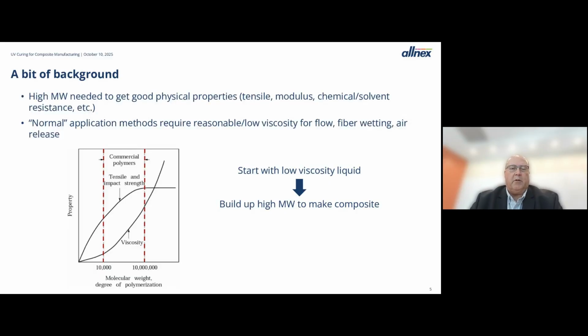So just a couple quick background slides. I'm sure that most people already know this, but just to get us rolling. In the world of polymers, in order to get good physical properties, good tensile properties, high modulus, chemical solvent resistance, whatever properties you're looking for, in general, you need to get to high molecular weight. However, as shown on the chart there, as you go to a higher and higher molecular weight, viscosity goes up accordingly. And normal application methods require some reasonably low viscosity material for flow, fiber wetting, air release, in general application. So in a lot of applications, we're going to start with a low viscosity liquid and build up to high molecular weight to make the composite, regardless of whether it's UV or thermal.